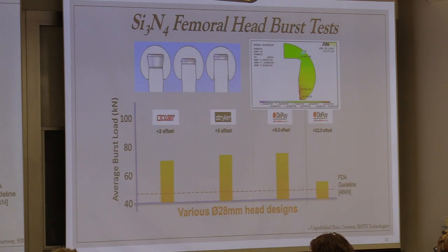Okay, so I pointed out the reasons for failure. One of them is fracture. The FDA has actually set a standard for components in terms of fracture, and they've done it at what are called various offsets. In the modular design, offsets allow the physician to adjust the device to make sure that the leg length of the patient is equivalent to his other leg. It depends on how far into the modular head you push the taper. So they have different offsets, and the most severe offset is, of course, a 12.5 offset.